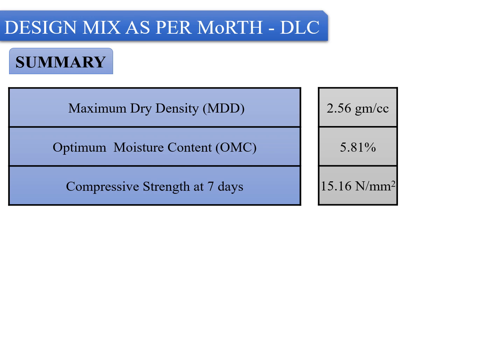That means the mixes are not produced in line with the design mix. There might be a change in the aggregate to cement ratio, or a change in the cement content in the mixes. Even though the percentage compaction is achieved, if the compressive strengths are not achieved, the stretch which is laid is deemed to be rejected.